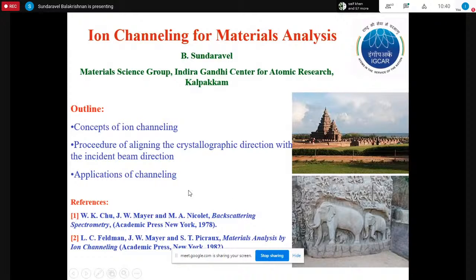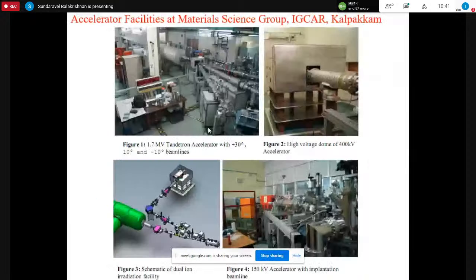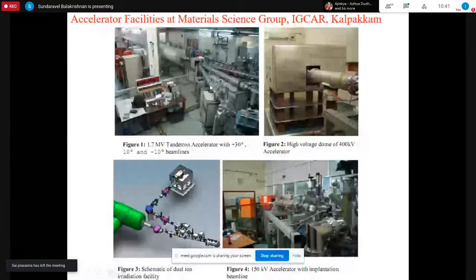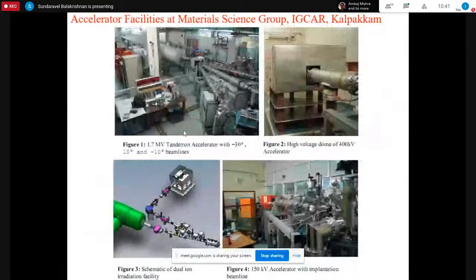For detailed understanding, one can go through two books, one by Chu, Mayer, and Nicolet, and another by Feldman, Mayer, and Picraux. In IGCAR, we have 4 accelerators, and most of our experiments on ion beam analysis and ion implantation use the 1.7 MV Tandetron accelerator. In our accelerator, there are 3 beam lines, and most of our studies are done in the plus 10-degree beam line, where we can do ion implantation and ion beam analysis techniques like Rutherford backscattering, elastic recoil detection, PIXE, nuclear reaction analysis, and channeling.